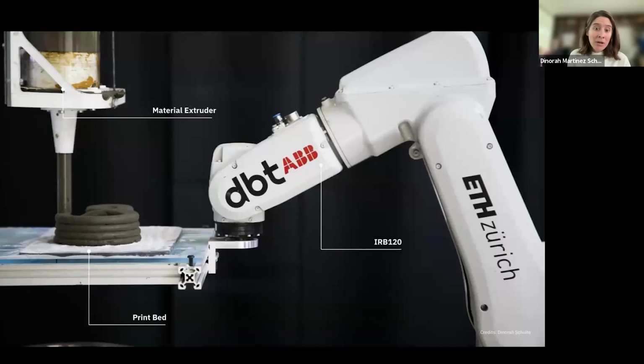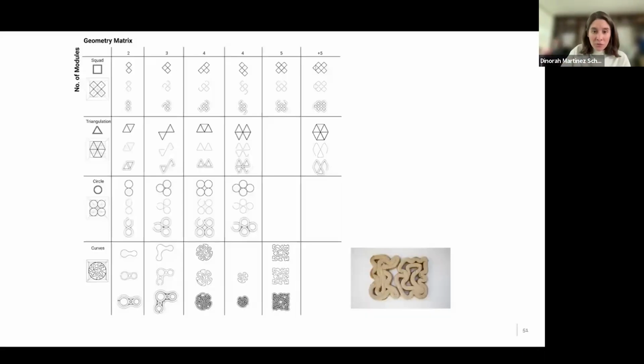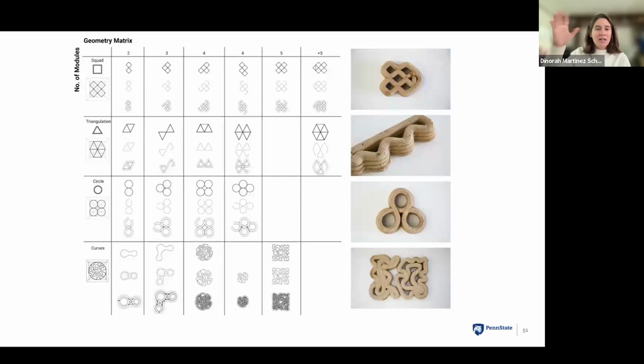So these are the fabrication tools that I have: the robotic arm, the material extruder, and the printing bed. But one of the important things about this project is that the material extruder is not moving. It's totally static. The tool that is moving is the printing bed. That is totally different, because when the printing bed moves, the whole geometry starts to move. So I did this geometry matrix, which is very basic, to start testing which geometry or which geometry direction works more efficiently with this kind of material. I did this matrix with squares, with triangles, with circles, and also with curvatures.